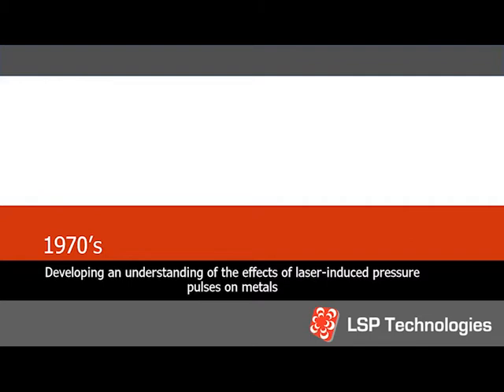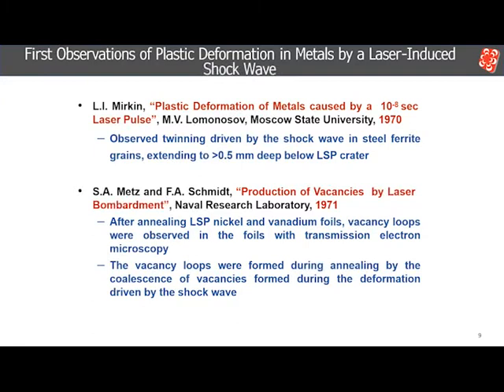Next, I'll discuss events in the 1970s when much of the exploratory investigation of laser processing was conducted. When it was realized that a significant shock wave could be produced in a metal surface by a laser pulse in air, it immediately generated interest in the effects it had on the target. These are the first investigations of the effect of a laser pulse-induced shock wave on the microstructure of a metal target. Mirkin shocked the steel target and observed deformation twinning in the ferrite grains extending more than half a millimeter deep below the shocked area.